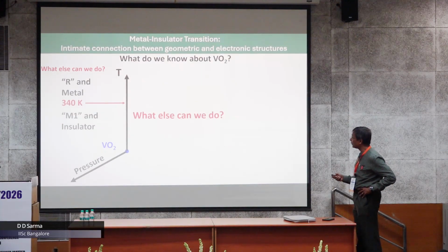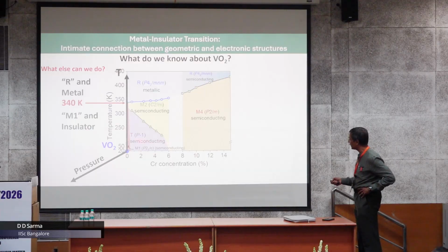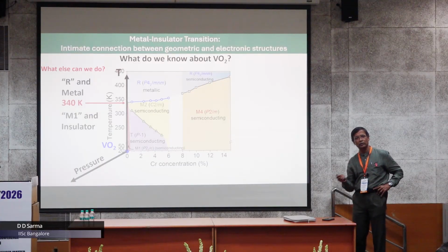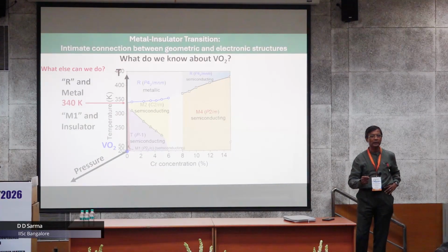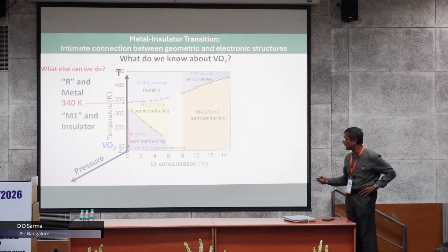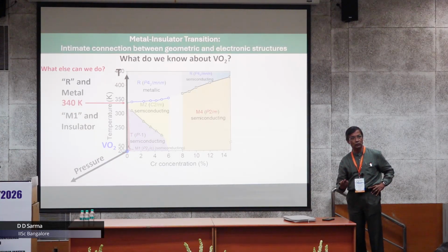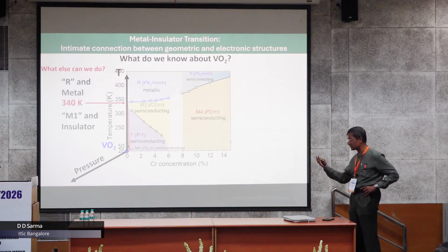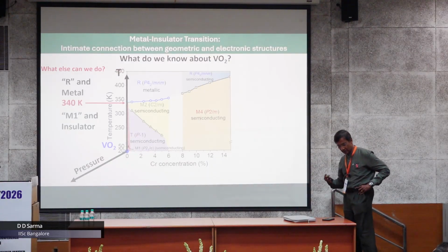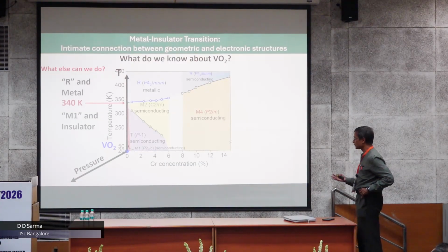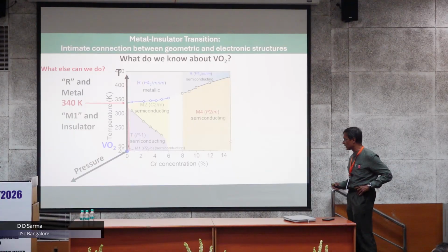We can start doping the system. For example, instead of vanadium at the vanadium site, which is a 4+ ion, I can put chromium, which goes in as 3+ ion. So basically, forget about what the ionic charges are, but what we are doing is to dope the system with holes, and I can deviate from the integer filling, and I know that has a tremendous consequence for the correlation physics, that at integral filling gives me an insulator, but as I dope, I go into a metallic state, as we know for the high temperature superconductors, colossal magnetoresistance, and almost every other example that we know of.